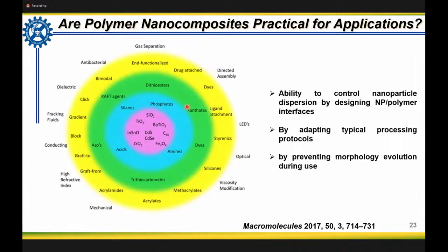So if the interface is very good, only then can we have better mechanical properties. Also, in certain cases, when we are using such modifiers while processing, unfortunately some of them will degrade. When the modifiers or surfactants, whatever we have chosen, degrade, the interface will again become very bad. That's why it's very difficult to produce reproducible results using such nanomaterials.